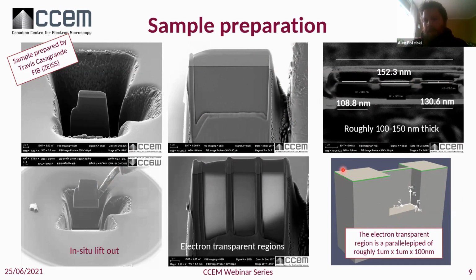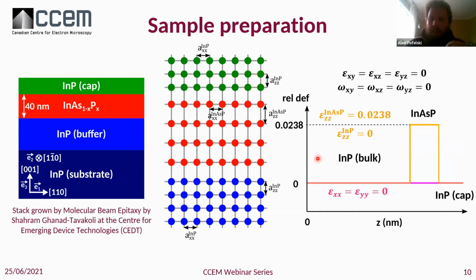They're supposed to be electron transparent. So this structure is important to keep in mind, because it's going to be subjected to strain relaxation, because we have some free surfaces that are happening here. So let's see an example of how this is going to affect your strain results.